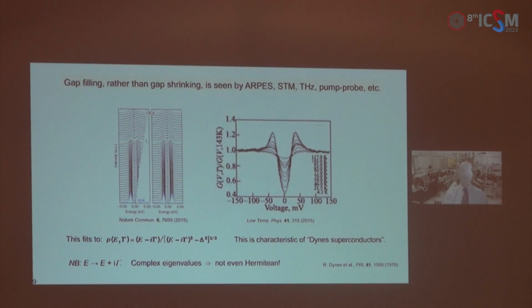Now, the same was seen also by ARPES, STM, specific heat measurements, etc., while adding some more details to the picture. In BCS, as you increase the temperature, the superconducting gap should shrink and close at Tc. But in cuprates, that's not the case. Instead, the gap fills in from below, which means that there is always a significant metallic density of states even at zero bias. And this increases with temperature. This can be fit well with the phenomenological Dynes formula, in which the real energy is replaced by a complex number. But note that this is very unorthodox. It is beyond standard textbook quantum mechanics, and the eigenvalues of Hermitian operators are real. So this also calls for some deep thinking.